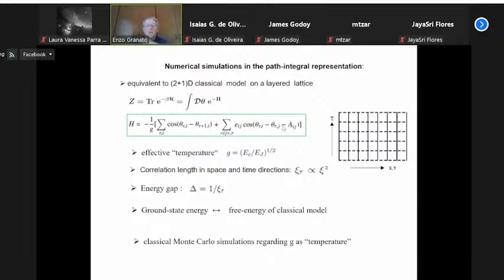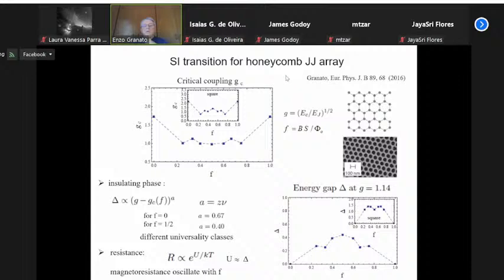But the quantities here are not operators; they are classical. You can use traditional Monte Carlo simulation to do the calculation. The mapping shows that this is a classical problem in which the effective temperature is equal to the ratio between the charging energy and the Josephson coupling. The correlation length is different in the time and spatial directions. They are related by an exponent z, which is the dynamic exponent. And the energy gap in the insulating phase is related to the inverse of this correlation length. And the ground state energy of the quantum problem is related to the free energy of this classical model. So we can use this method to perform the numerical simulation. For the superconductor-insulator transition in a periodic array, the appropriate model is a model on a honeycomb lattice.